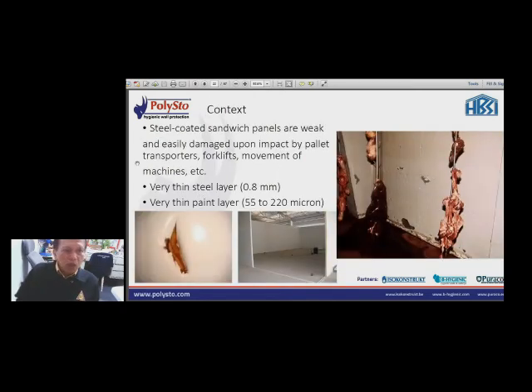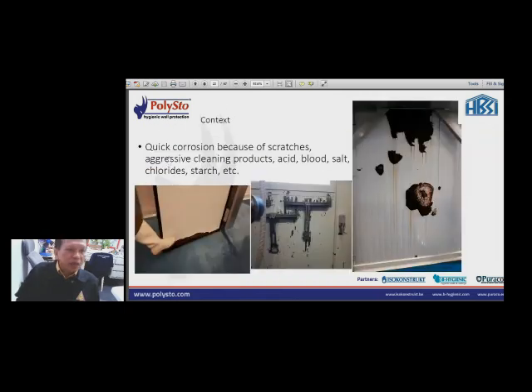Steel-coated sandwich panels are weak and easily damaged upon impact by pallet transporters, forklifts, and movement of machines. Very thin steel layer, about 0.8 millimeter thick, and very thin paint layer, 55 to 220 micron thick. So you would see here that the thin layer would soon deteriorate, because it is very thin. Quick corrosion because of the scratches, aggressive cleaning products, acids, blood, salt, chlorides, starch, among others, will damage this finish of the wall.